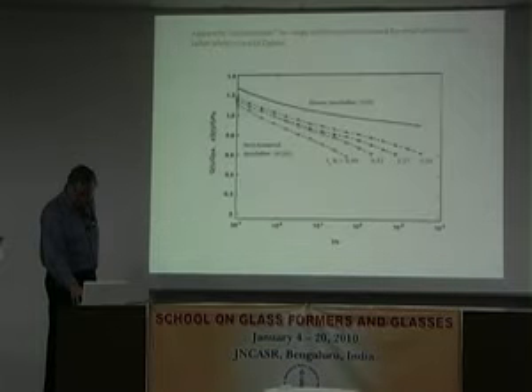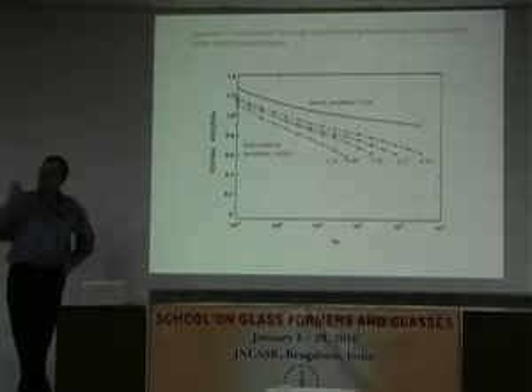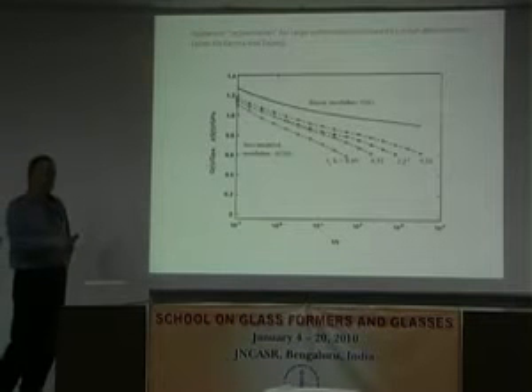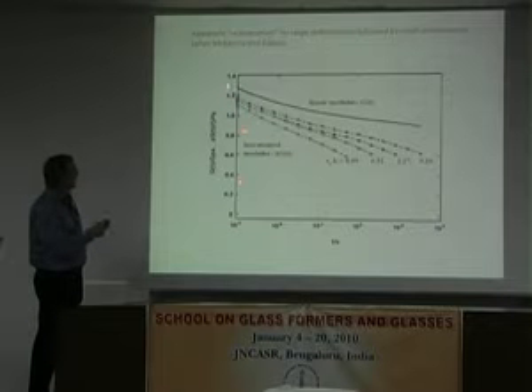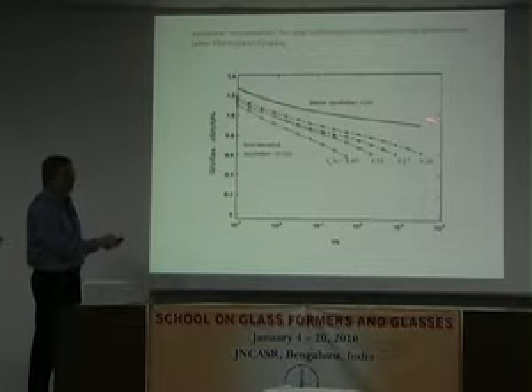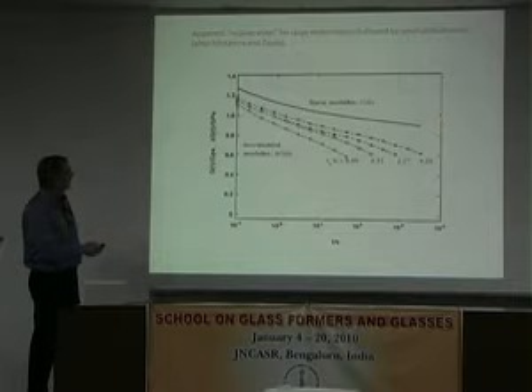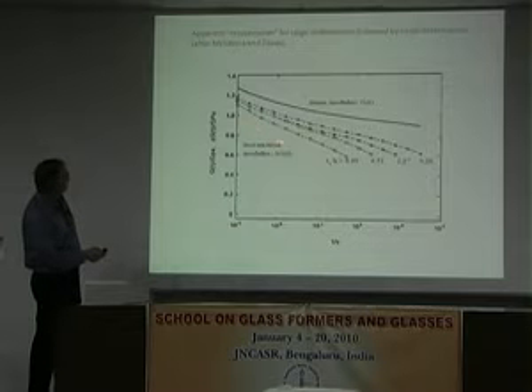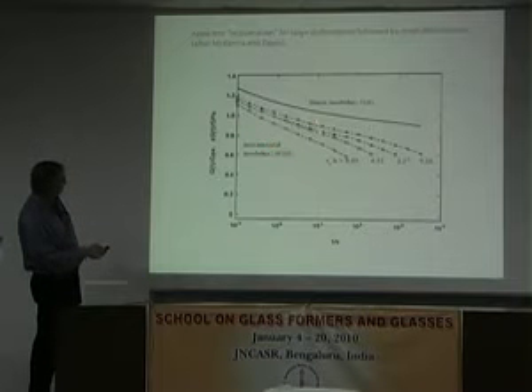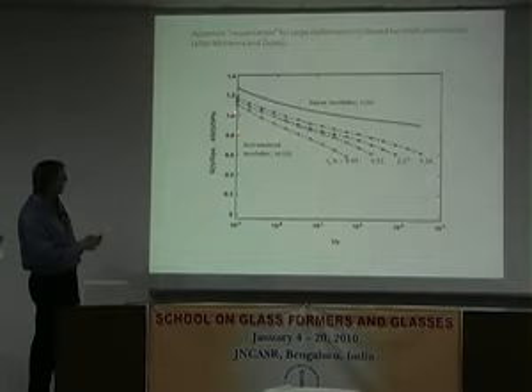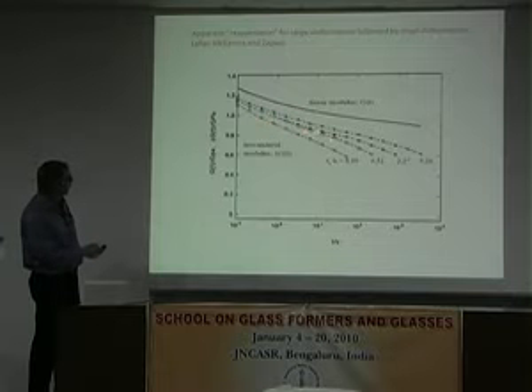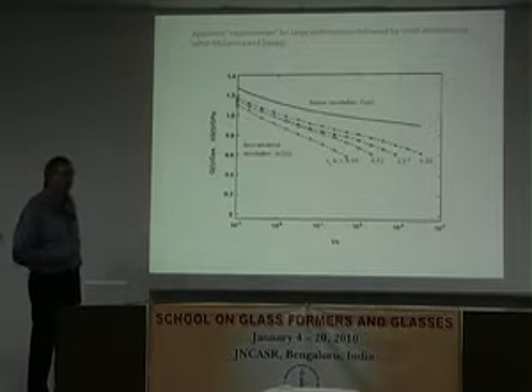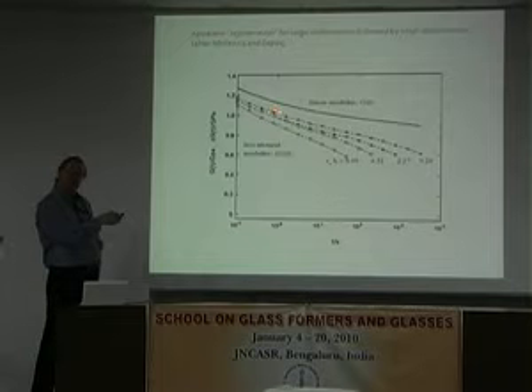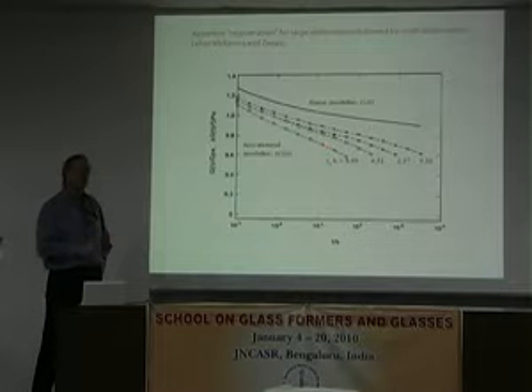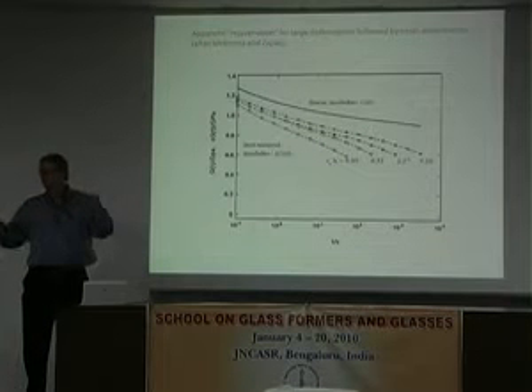So here's what people saw and interpreted as rejuvenation. Here's your linear viscoelastic response modulus, and when I put a large deformation on it, and I don't actually remember, it's like 5% strain in polymethyl methacrylate, what we find is that it shifts to shorter times and then moves outwards. Okay? So it looks like it's been rejuvenated, and then aging starts over again. Okay, that was the interpretation that was done.